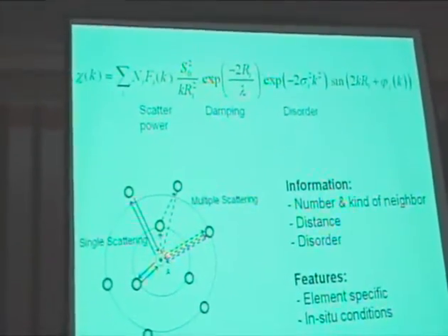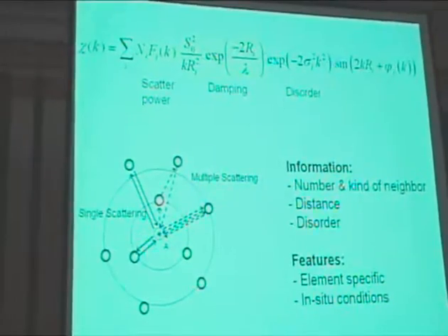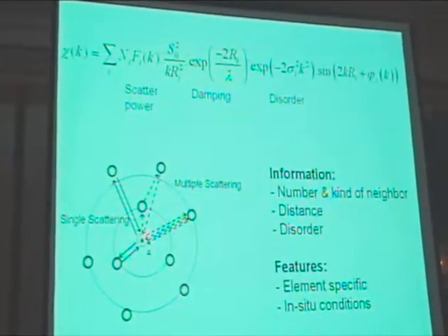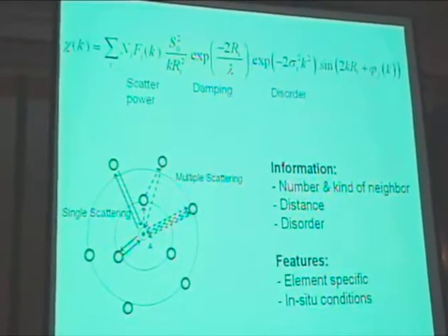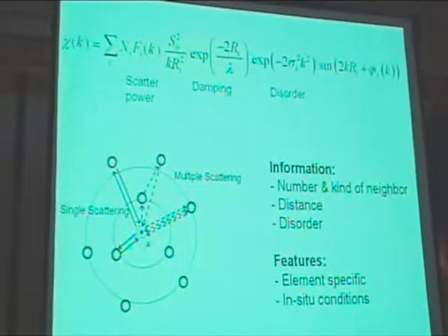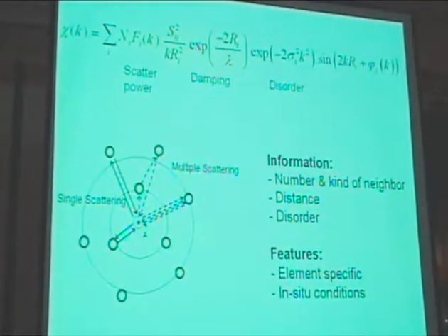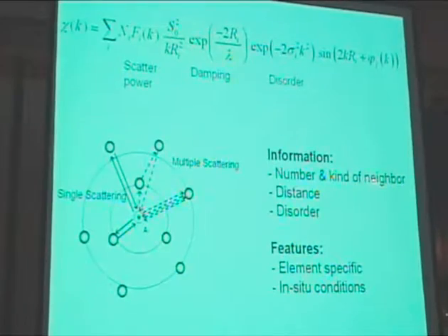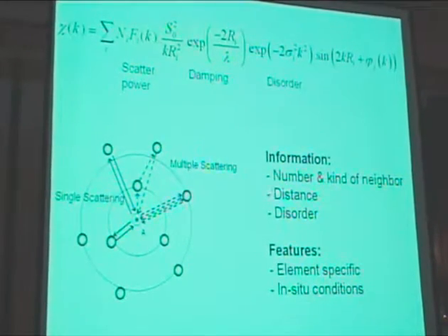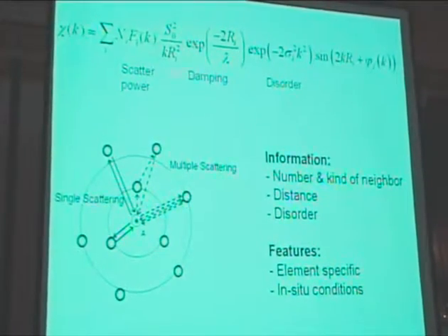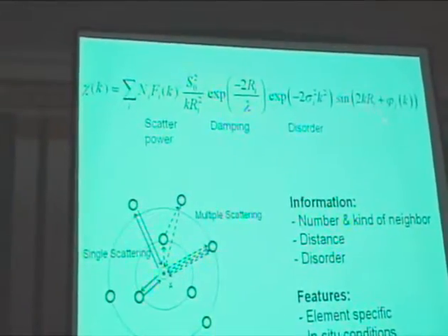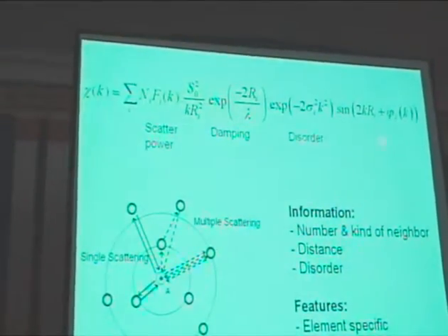And because this interference effect is dependent on the type of atom, especially the backscattering atom, and on the distance, you can get information. If you analyze those peaks, you get information on the number and kind of neighbors, on the distance, and maybe on the disorder. Because you end up with a formula, which I will not go into too much, but it looks like this.